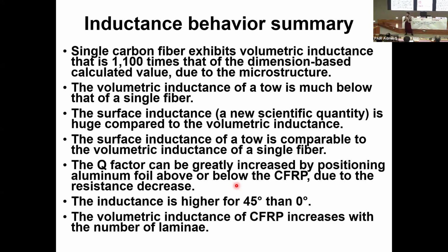So this is a summary of the inductance behavior. Single carbon fiber exhibits volumetric inductance that is 1,100 times that of the dimension-based calculated value due to the microstructure. The volumetric inductance of a tow is much below that of a single fiber. The surface inductance, a new scientific quantity, is huge compared to the volumetric inductance, and the surface inductance of a tow is comparable to the volumetric inductance of a single fiber.